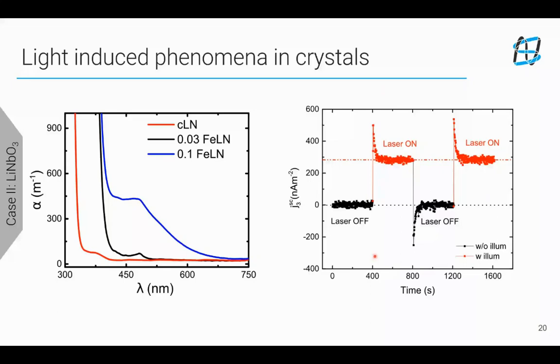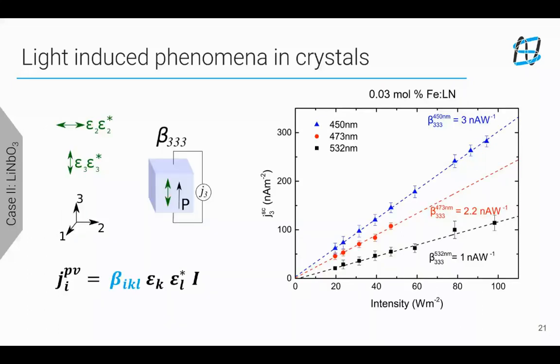And so what we did was we changed the polarization of light, either parallel to the polar axis of the crystal or perpendicular to the polar axis of the crystal. And we measured the short circuit current charge density along the polar axis. If the light polarization is parallel to the polar axis, then the bulk photovoltaic tensor beta ikl becomes beta 333, because 3 is the polar axis, and 3 is the index we give for the current which is measured along the polar axis.